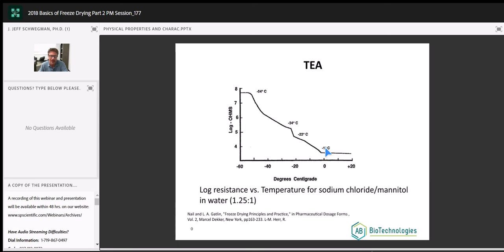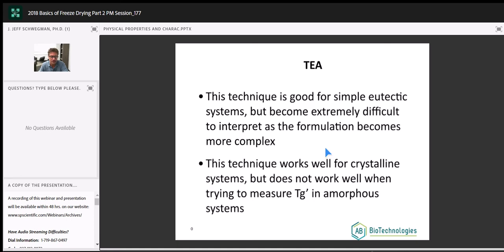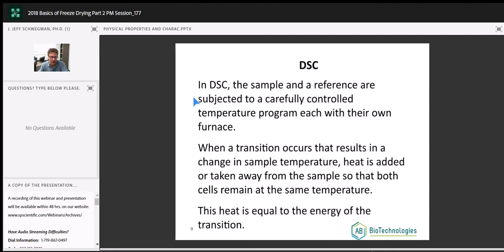When we change the ratio, I don't know what we get. There's multiple transitions going on. We don't know what they represent. So again, it becomes much more difficult to interpret what's going on with this. So again, as I mentioned, this technique's good for simple eutectic systems, have some ionic species in them. Again, when we start talking about glass transition and very complex formulations, it becomes very difficult to interpret.